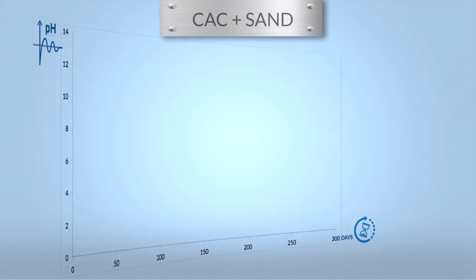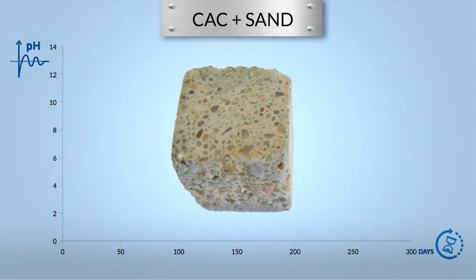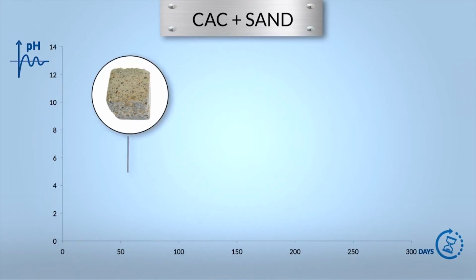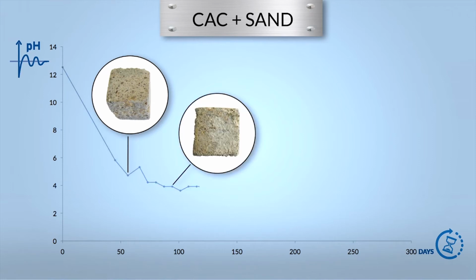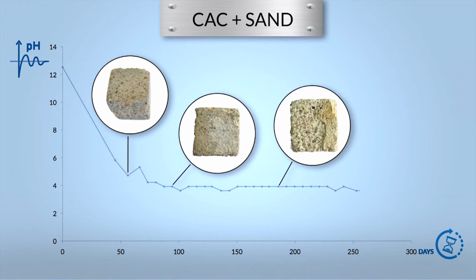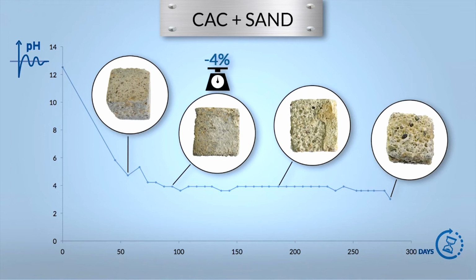Just beside the previous series of cubes, specimens made with a calcium aluminate cement were exposed. After the same 9 months of exposure, the visual damages are very limited. The cubes have retained their shape. They're still sound and solid. The surface pH stabilized around 3.8 after 3 months. This is because the calcium aluminate cement inhibits the bacterium metabolism, which stops the transformation of H2S into sulfuric acid. The weight loss after 9 months is only 4%.